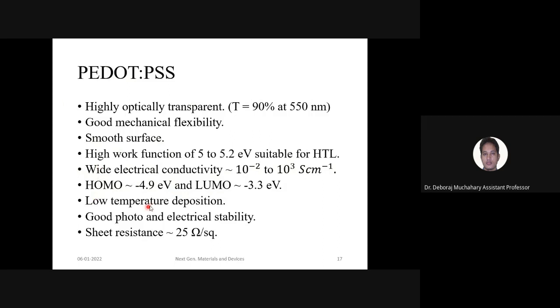One more thing is low temperature deposition. Because these are polymers, and when we go for silicon processing, the silicon processing is around 1000 degrees centigrade or even more than that. These are very high temperature processes, due to the doping process, and some problems arise. Here, if we use PEDOT:PSS, then you can deposit it in a low temperature environment also. So there is a good advantage in terms of fabrication.